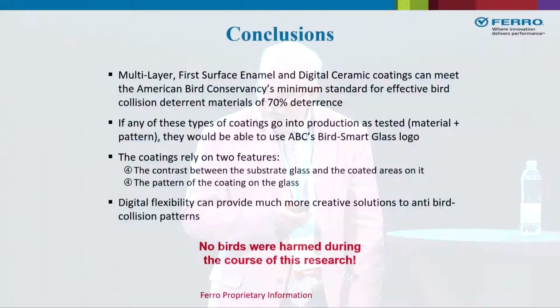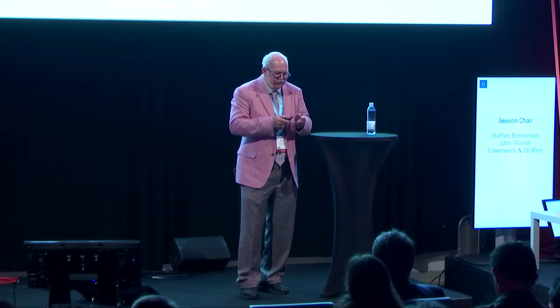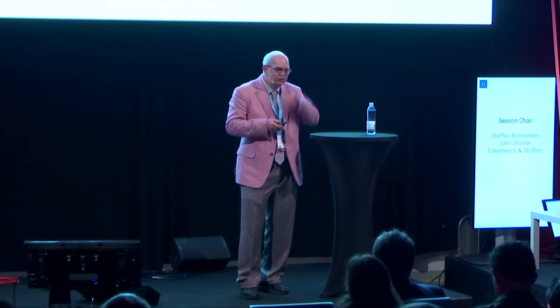So here are some conclusions. We have the multi-layer first surface and digital ceramic print. They can all meet the American Bird Conservancy's standard for effective bird deterrence. And so if any of these coatings were printed with the material and with the pattern, then they could use the bird safe logo for the glass.